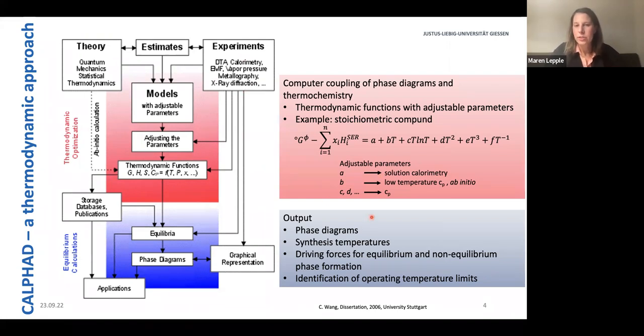Here I chose some examples. So A can be fitted to solution calorimetry data, for example. B, which stands more or less for the entropy, can be fitted to low temperature CP data, or data which is gained from ab initio calculations. And the higher adjustable parameters can then be fitted to the heat capacity, for example.